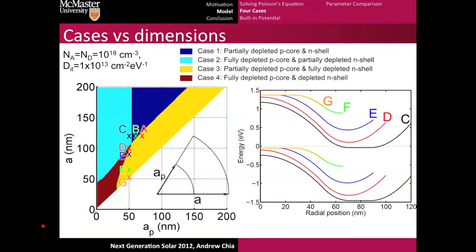Lastly, if we have a one nanometer thick shell, we're happy to see that the single-doped P-doped nanowire case is recovered. Now, if you look at each of these band diagrams, you'll see that the built-in potential is constantly decreasing or is constantly changing.